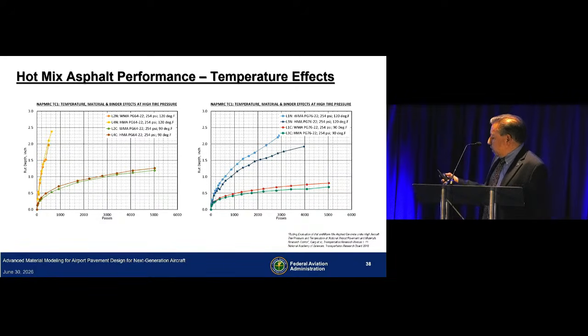Same thing for polymer modified binder. The right curve is for polymer modified binder PG 76-22. And of course, it gives better performance than the unmodified binder. But again, the effect of temperature is fairly significant. At 120 degrees, sections are failing in around 600 to 800 passes, whereas at 90 degrees, these curves were approaching asymptotic, which means it would take an enormous number of passes to reach failure. So we stopped testing at around 5,000 passes here.